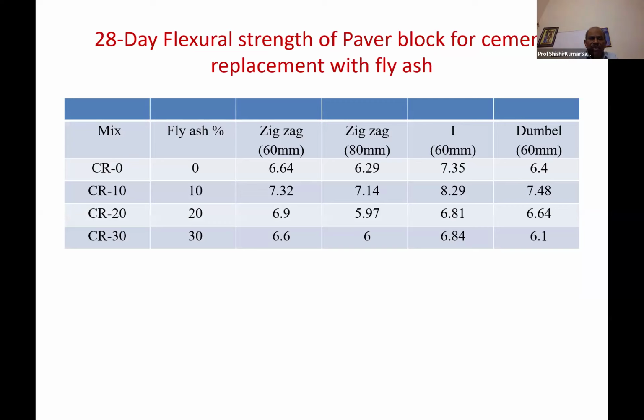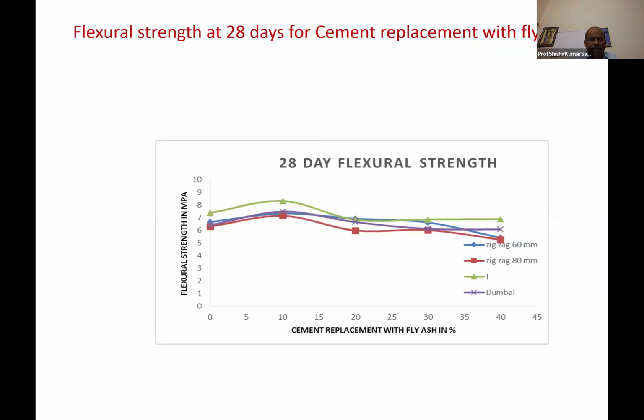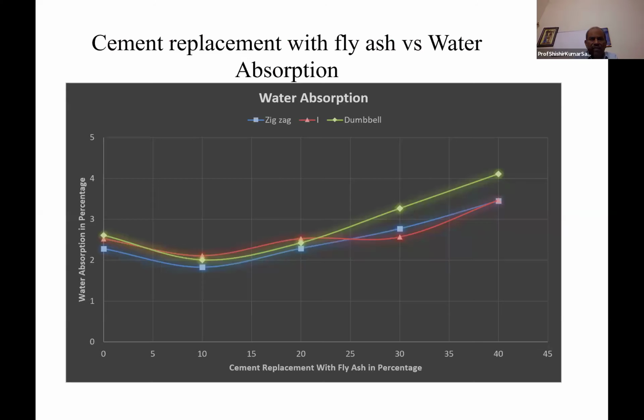Cement replacement with fly ash for different shapes of ICBP. This is flexural strength. All values are above 4.5, which makes them suitable for use as a pavement material. Then water absorption. I think the satisfying level is 4%, and everything is below 4% except this one.